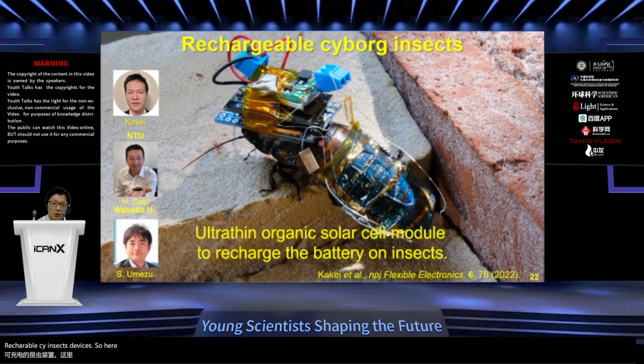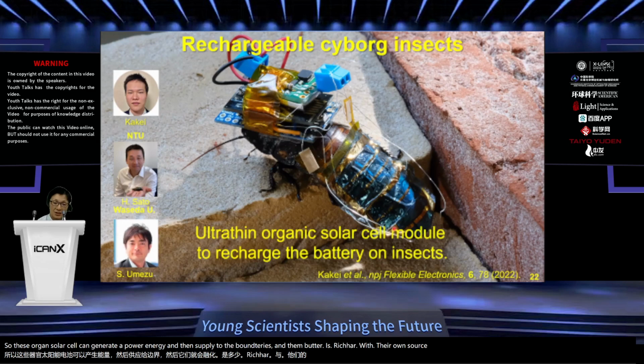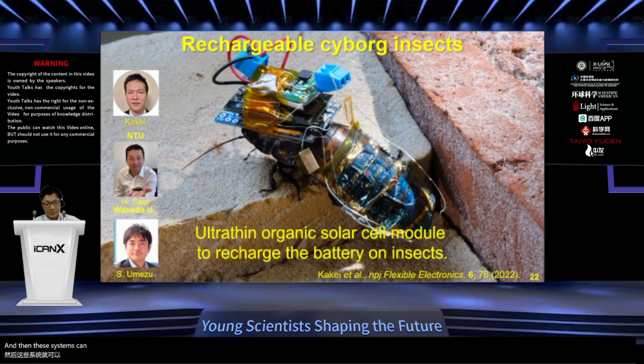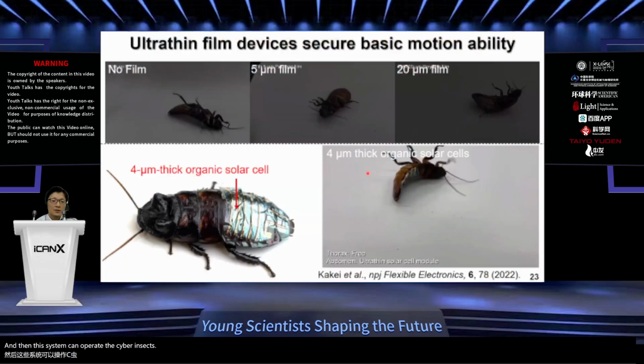So here is a photograph of the actual cyborg insect that we fabricated. The very thin organic solar cells are adhered onto the insect abdominal surface, and the other rigid components are integrated, adhered onto the thorax of the insect body, as shown here. So this organic solar cell can generate power and supply it to the battery, and the battery is recharged with the organic solar cell energy. And then this system can operate the cyborg insects. The important finding through this research is that thinness is a very important parameter to achieve the basic motion ability of insects.